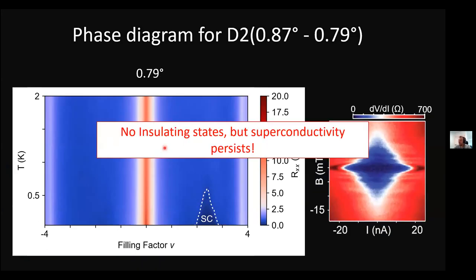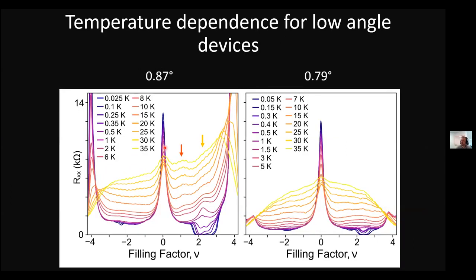And especially for this really low angle device, there's no insulating states and superconductivity persists. And when I say there's no insulating states, I actually mean also the full filling states are not insulating. So this is just a comparison of the 0.87 degree and 0.79 degree. And these are several line cuts.